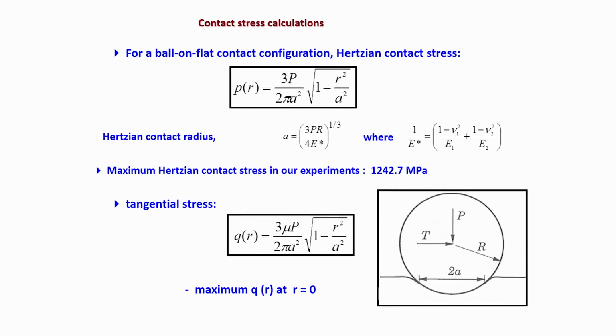One can explain or rationalize this formation of the microcracking by calculating the Hertzian contact stress, and this formula you have seen before, but to repeat, PR is the Hertzian contact stress, P is the load, R is any given radius, a is your contact dimension, and this is (3PR/4E)^(1/3), and accordingly the tangential stress can be calculated as QR equal to 3 mu P divided by 2 pi a square root of 1 minus R square by a square.